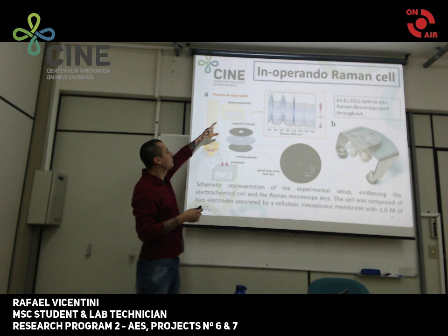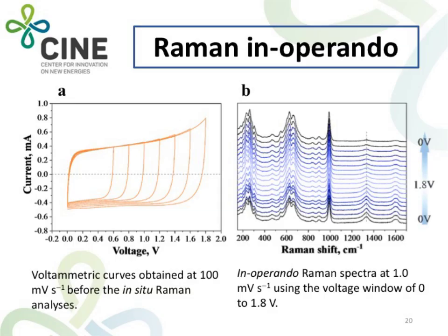Before the Raman in operando studies, we made a cyclic voltammetry at 100 millivolts per second, just to verify the proper function of this cell. And on the right side in figure B, we can see the in operando Raman spectra at 1 millivolt per second. Here, we used a voltage window of 0 to 1.8 volts. From this data, we can plot these two graphs. On the left side, in figure A, we can see the Raman band of sulfate as a function of applied potential. And on the right side, in figure B, we can see the D-band position and the D-band intensity as a function of applied potential.